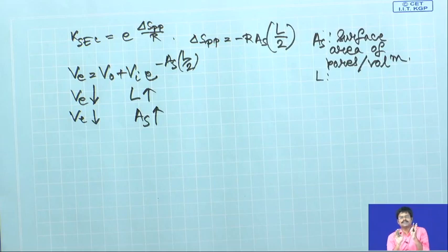Elution volume goes down means that particular compound will come out first, earlier, because elution volume is correlated to time. So, at lower elution volume it is coming out means initial phase of the column it will come out. Now, V_e is going down with increasing L, that means if polymer size goes up, it will come out first, earlier. Initially I told you this same thing in a physical interpretation sort of way, and now I am showing you mathematically that it is the same.